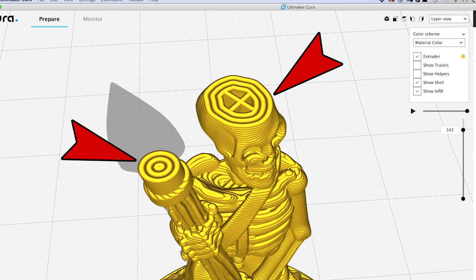Well, for me, I like printing my miniatures with three shells. This is with a 0.4 millimeter nozzle, and let's do a little math here. The total wall width on either side of this mini is going to be 1.2 millimeters because it's three layers and each layer is 0.4 millimeters. So 0.4 times 3 is 1.2 millimeters. You double that because you have a wall on each side. That means any single layer of your miniature, if it's thick enough, without any infill, is going to be 2.4 millimeters thick of plastic. Now that's a tenth of an inch of plastic for a 1-inch tall miniature. That's insane. If you can break through that, you're going to just break your miniature regardless of what the infill is.